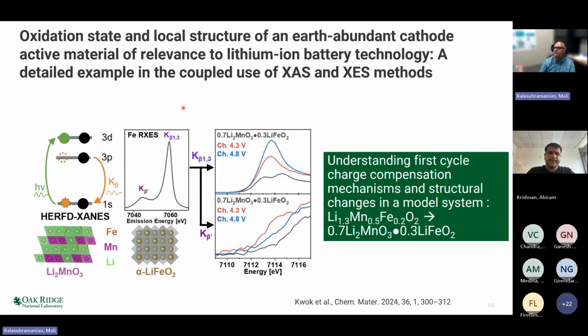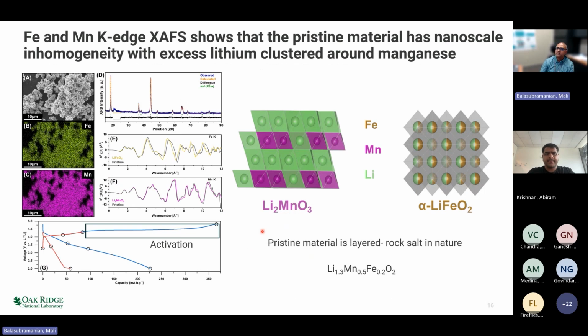So to show how this happens, before I go there, let me just describe this sample. This sample, just like the previous example that I showed you, does not form a completely disordered solid solution, but forms a composite material with Li2MnO3 like character and rock salt LiFeO2 like character. Although the material appears uniform on the micron scale, on the length scale of a few angstrom, the material has this inhomogeneity at a nanoscale region. You can see that the Li2MnO3 is again similar to the pristine Li2MnO3. The manganese edges are similar, while the iron edges are of LiFeO2, which is a cubic LiFeO2, is very similar to the pristine.